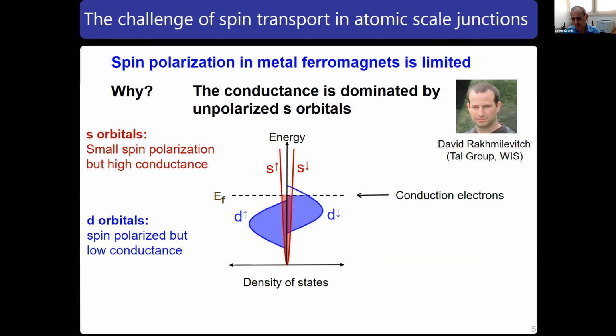They are spin polarized, but they barely contribute to the conductance because they're not at the Fermi level, they're far below it. So the orbitals that are at the Fermi level are typically s orbitals, but they are not so polarized. So it turns out that you can have a magnet, even a very strong magnet for that matter, which would still be a fairly weak material as far as spintronic applications are concerned.